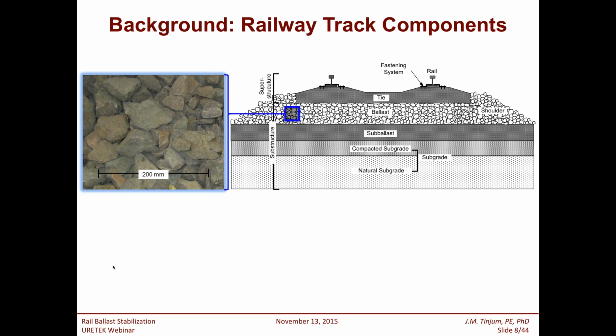With much of the United States infrastructure for rail being out there for, we're working on tracks that have been there for 120 years. There's going to be sub-ballast below that, either for new construction or the sub-ballast that 20, 30, 40 years ago used to be the main ballast section, and as maintenance activities occur over the years, new ballast is placed on top and the sub-ballast just becomes lower into the system. This is important to keep in mind because the sub-ballast is very much a target of our interest and our research because that sub-ballast is going to be degraded, it's going to have fines in it, and it's going to be apt to retain moisture, and thus not structurally transfer the load as well as we would like.